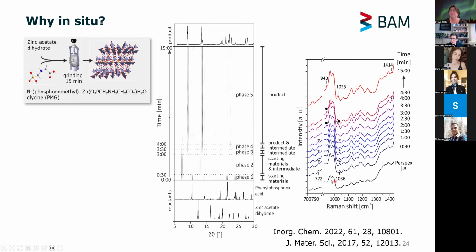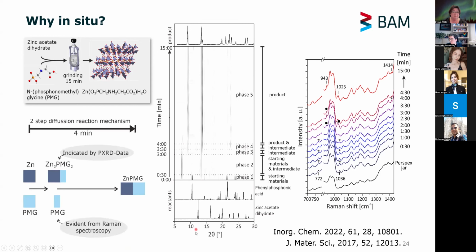The Raman data plot is more or less the same thing. You can monitor here the bands of the ligand, and you can see here the contribution of the final MOF that is formed, and it is more or less in the same regime. But Raman and X-ray, of course, monitor different things. In X-rays we see the crystalline phases. Raman would also tell us a bit about what's going on in the amorphous regime. And here Raman tells us that our ligand persists a bit longer, where we can also see from the X-ray data that we have an intermediate compound with this stoichiometry. So both together really give us a cleaner picture of what's going on throughout the reaction.